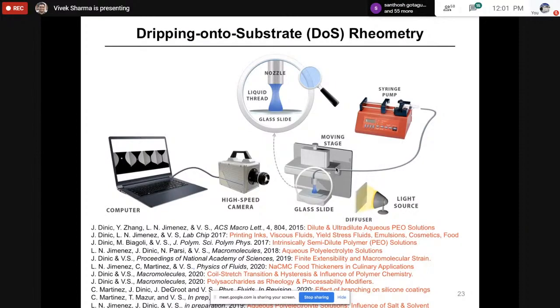So what we do is we create a liquid bridge which looks similar to the liquid bridge that's found in Caber without using any moving parts. So we take a nozzle, place it at a fixed distance from a glass slide or a substrate, release a finite amount of fluid so that you get formation of this nice hourglass shape. The neck is thinner than the sessile drop and the pendant drop. The capillary stresses take over, they squeeze the neck, pushing the fluid out, and that neck thinning dynamics is governed by the same balance of forces that applies in Caber or stretch liquid bridge configuration or in jetting or in dripping. And by analyzing this neck thinning dynamics, we can make measurements of material properties that influence processability, extensional rheology response, and so on.